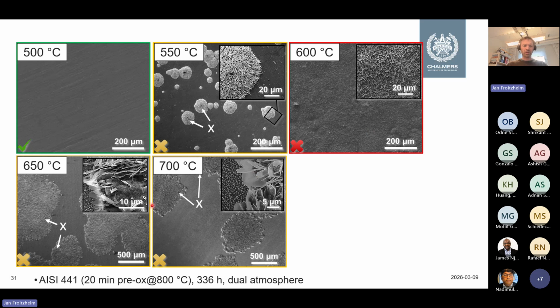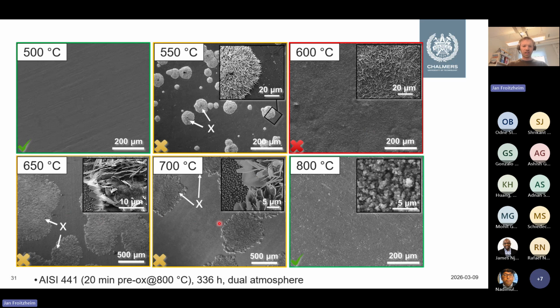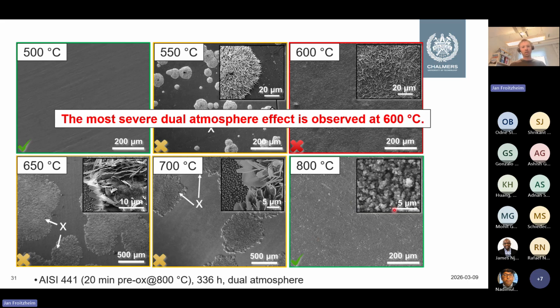Interestingly, when you increase the temperature further, you get a more protective scale again, and at 800 degrees C you have a completely protective scale again. So the most severe dual atmosphere effect is observed at 600 degrees C, and that is a little bit unusual. Usually the higher the temperature goes, the worse things get, and if you go down in temperature things get more manageable. But here, this is not the case.